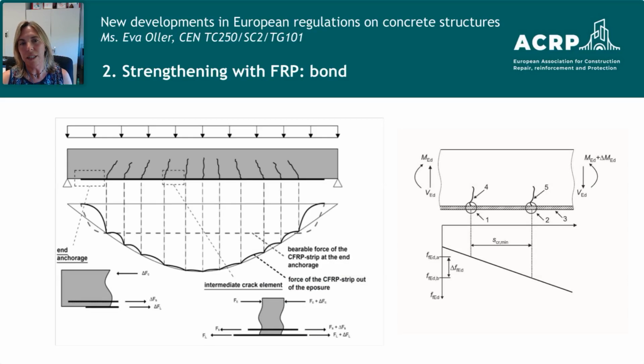We should check that the force transferred by the laminate to the concrete in between the laminate end and the first crack is properly transferred to the concrete. And also between each pair of cracks, we should check that the increment of tensile force between two subsequent cracks is properly transferred by bond to the concrete surface. By doing so, we are going to guarantee that this type of failure is not going to occur.